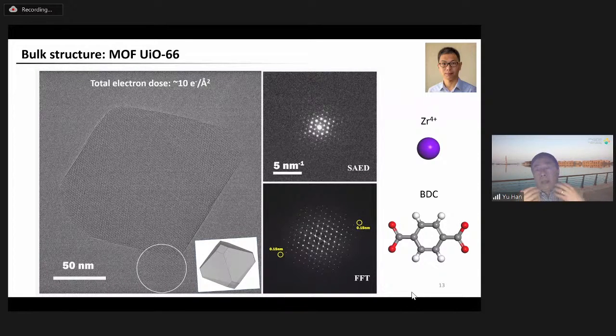And therefore, this ensures that the observed local structures are inherent structures, not the result of beam damage effects, right? It's meaningless to image local structures under conditions that can damage the bulk structure. So this is our logic. We don't know what imaging conditions are safe, so we use a known bulk structure as a reference to prove the imaging conditions are safe, and then we can image the so-called local structures, because nobody knows what local structures look like, right? So we have to make sure the imaging conditions will not bring structure damage. This is why, whenever possible, we always start from the bulk structure.